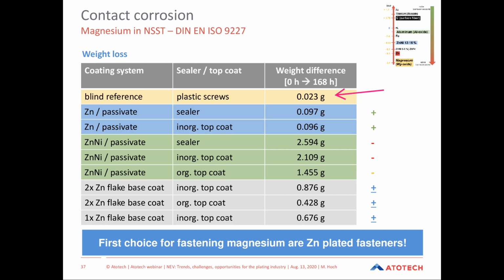When we look at the zinc plated parts, we lose approximately 0.1 gram of our magnesium plate. So there is very low corrosion. Whereas looking at the zinc nickel, we lose up to 2.6 grams of the magnesium by corrosion. So we get very severe corrosion with zinc nickel. And as already mentioned, the zinc flake systems are somewhere in between the galvanic zinc and the galvanic zinc nickel systems. So the first choice for fastening magnesium are zinc plated fasteners.